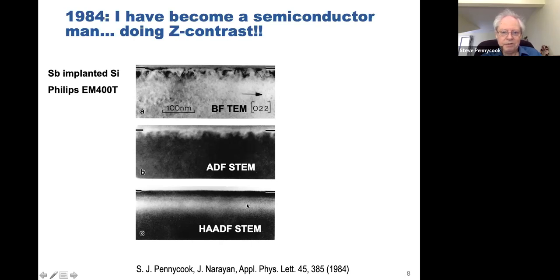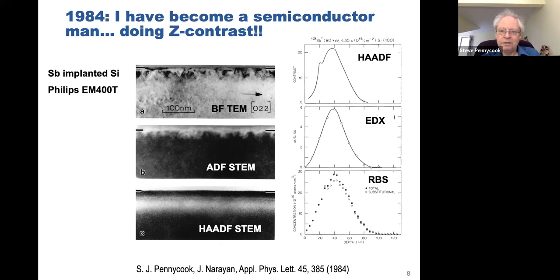But if you go to high angles, you see it completely changes. The diffraction contrast goes away. And what you see here is actually the dopant profile. This is the implanted antimony. And the profile from the image matches the EDX profile and also the profile known from Rutherford backscattering.